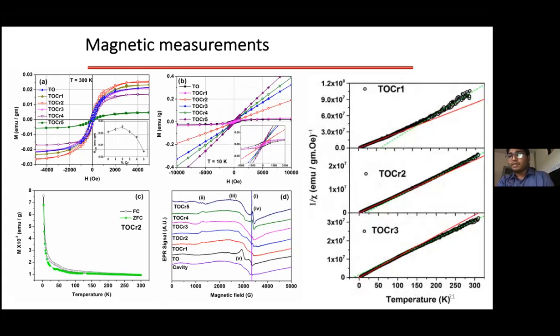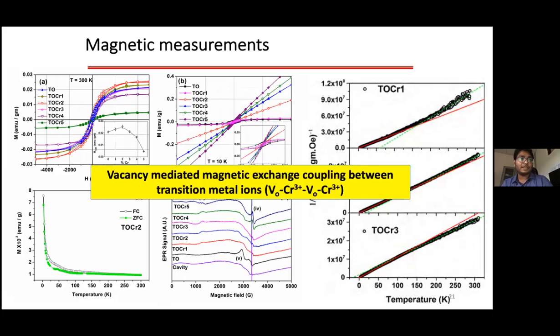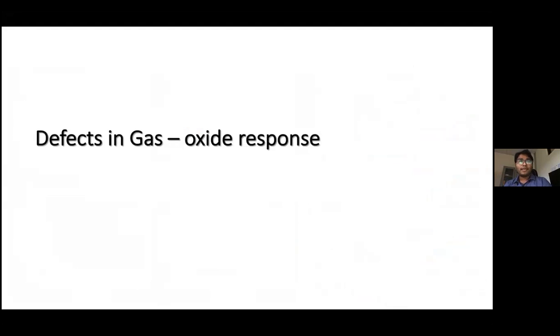And then the Curie-Weiss plot further confirmed that it is ferromagnetic up to 2% chromium, and then when it went to 3% doping, it showed a negative intercept on the Curie-Weiss plot, which means there was an antiferromagnetic ordering taking place. So this was explained, as I said, by the vacancies now coupling through some of the substituted chromium sites. That is some kind of a superexchange which is taking place among these different magnetic ions.